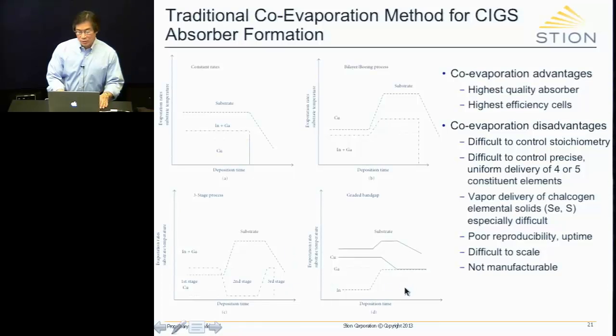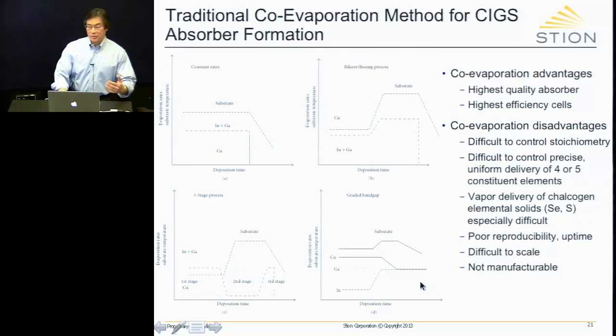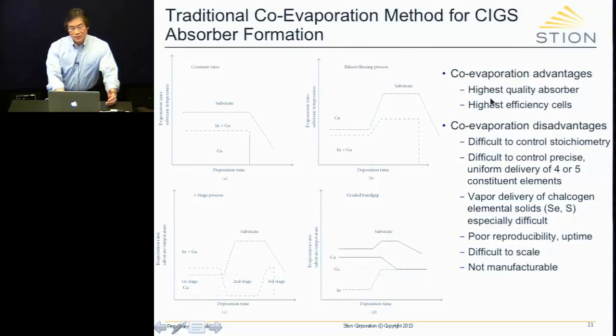And of course, you can do it in a way in which you can grade the band gap as well, so you can tailor how the carriers are extracted from the material. But the important point here is that this is a co-evaporation process. It gives you the highest quality absorber, no question at all. The highest quality absorber and the highest efficiency cells if you make CIGS. The unfortunate problem with this is that it's difficult to control the stoichiometry of this method. And it's particularly difficult to control the stoichiometry over a very large area.